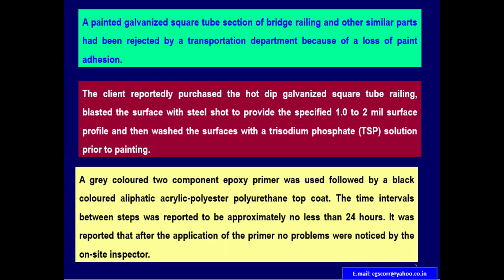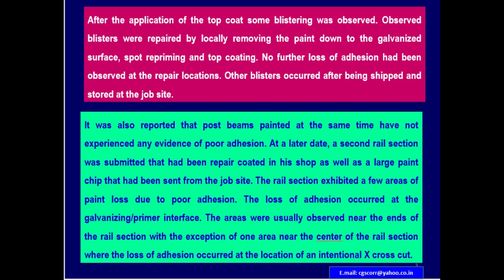A grey colored 2-component epoxy primer was used, followed by a black colored aliphatic acrylic-polyester polyurethane top coat. The time intervals between steps were reported to be approximately no less than 24 hours. It was reported that after the application of the primer, no problems were noticed by the on-site inspector. After the application of the top coat, some blistering was observed.